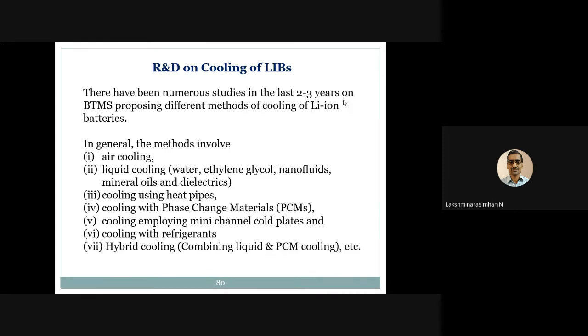You can have air cooling, you can have liquid cooling. Liquid should not be in touch with the lithium ion battery electrodes, because we all know that it's very sensitive. You cannot have liquids in contact. If you want to use water because of the high heat transfer coefficient and low pumping work required, still use it under a non-contact or indirect method. So you can use things like nanofluids, mineral oils, dielectrics. Using dielectrics is best because you can even immerse the battery. Dielectrics are not going to conduct electricity, so therefore you are cool in this thing.